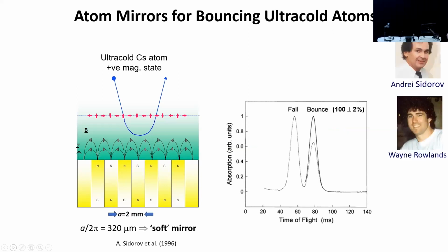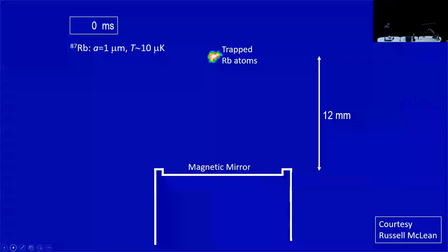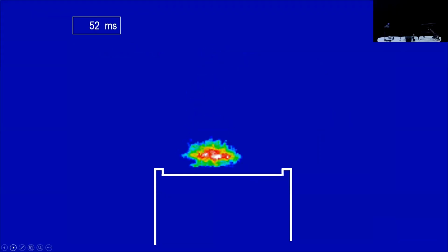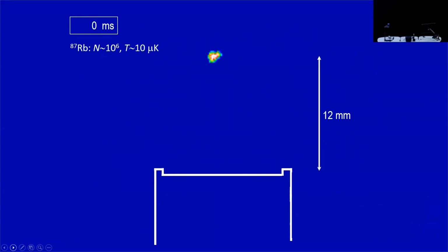So the experiment was Andrei Sidorov and Wayne Rowlands were involved in this early work. And the first work was done with cesium, and we saw 100% bounce, which was very encouraging for a first experiment. And then, of course, much better mirrors were made, and this shows a period of just 1 micron, which means it's a very hard mirror. It means the atoms bounce from very close to the surface. And for rubidium, this shows the atoms bouncing. After a while, they warm up, they spread out due to the finite temperature, bouncing from 12 millimeters. From these sorts of mirrors, you should be able to bounce from about 2 meters.